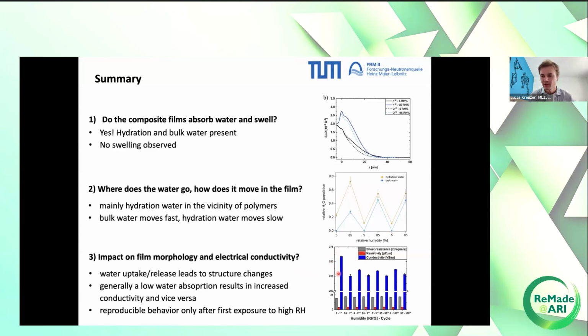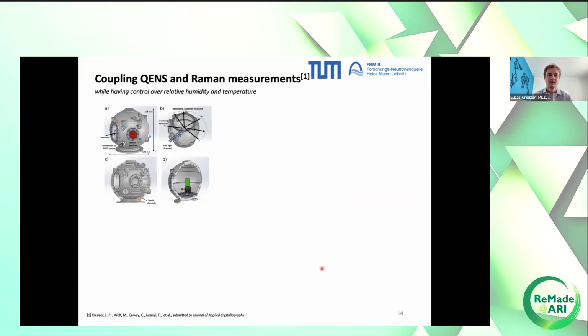And if I have just two or three more minutes, I would like to show you one other thing, which I think is very, very cool. I talked a lot about QENS and the advantages of QENS, but one thing QENS cannot do is distinguish whether a water molecule is sitting close to a PEDOT:PSS chain or close to a CNF chain. But there's another technique called Raman spectroscopy, which measures more the polymers. It probes the vibrational energies of functional polymer groups, and these change with hydration. So there we could actually distinguish between the different polymers, and that's why having a combined setup where you can couple QENS and Raman simultaneously would be super nice.